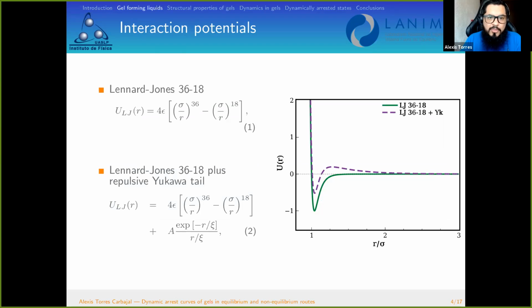To model these gels, we use interaction potentials that are attractive at short range, like the Lennard-Jones, given here in equation 1, and the Lennard-Jones with a Yukawa repulsive tail that is of long range. And in this sense, these promote the formation of these bonds that eventually, according to the thermodynamic conditions of the system, form the network that finally we can establish is a gel.